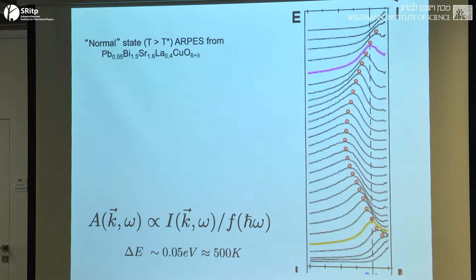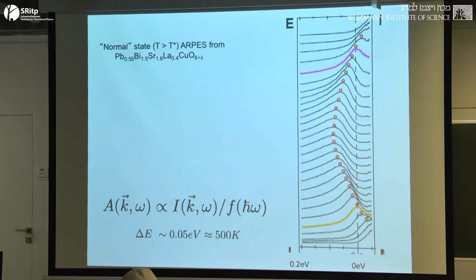Let's just take one of these. And what you see is the scale here is 0.2 eV. So here we're at 172 Kelvin. And I don't know, by eyeball, the width of this peak, I said the half width is something like 0.05 eV. So something like 500 Kelvin or something.